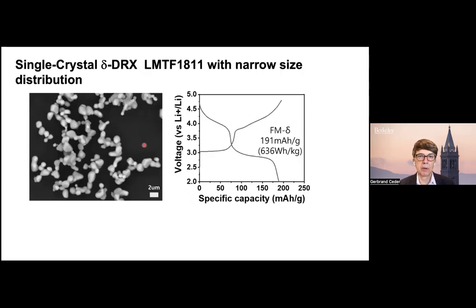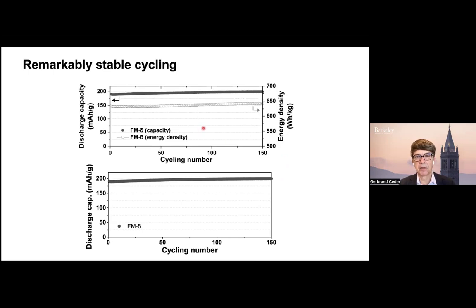Some unpublished work: if you play with the single crystal particle size, you can get the specific energy up. Here I'm showing single crystals between 1 and 2 micron. You get about 640, and in other work we're now approaching about 700 watt hours per kilogram in this DRX. Again, these materials cycle extremely stable. This is the energy density. This is the capacity, which sits roughly at 190 to 200 milliamp hours per gram. And energy density and voltage are very stable.